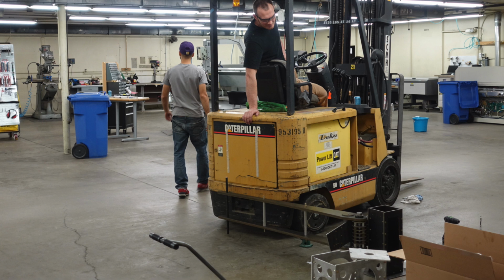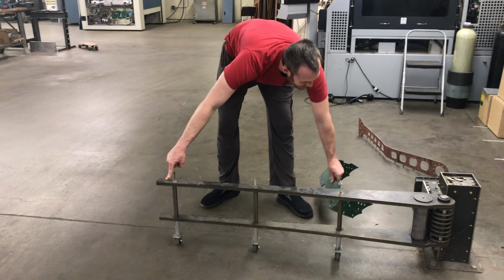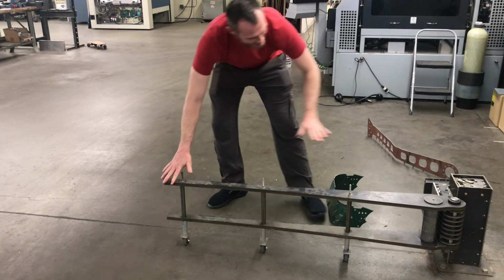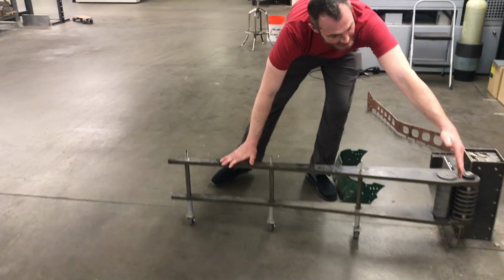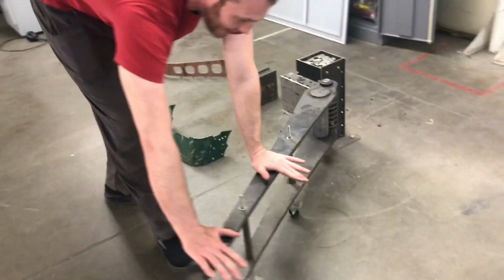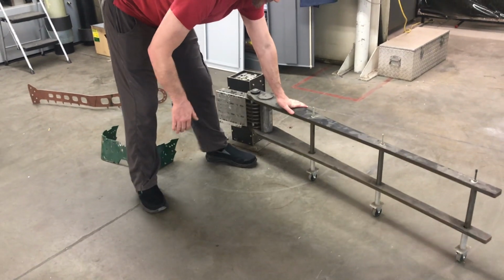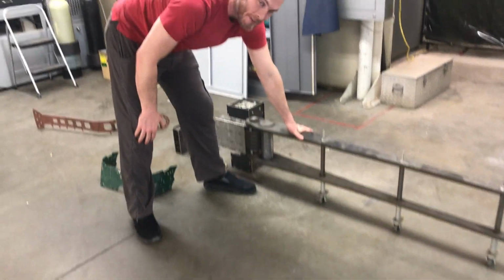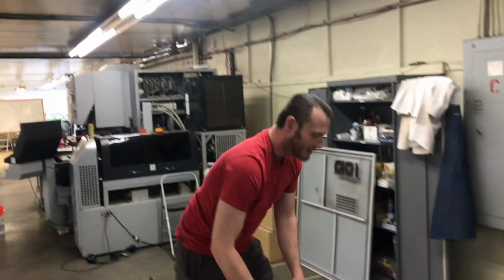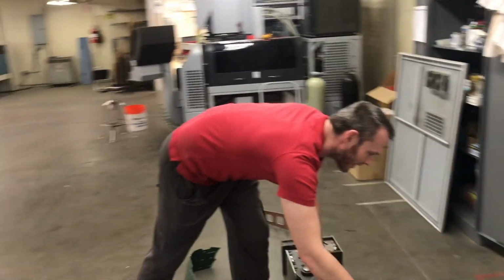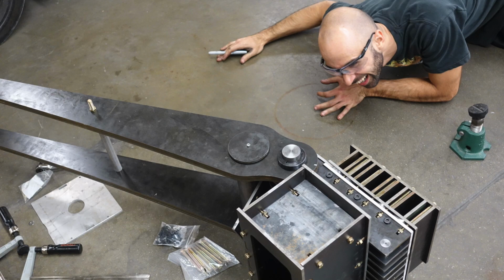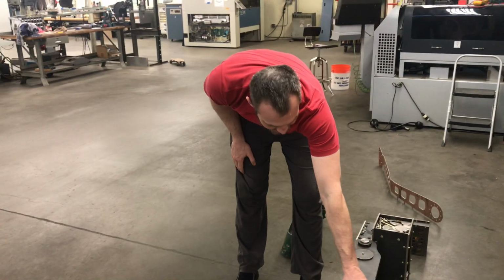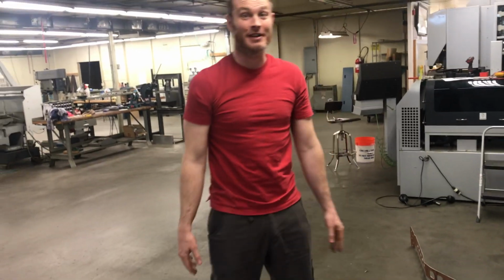We had to drive the forklift against this end of the arm. So we don't have any control at all. And so once you have your piece clamped here, sticking out into the room, you then drive this around, not to 90 degrees if you need a 90-degree bend, but because this material is so strong, you bend it to about 140 degrees, maybe 50 degrees of overbend, and it springs back from that to 90 degrees. That took a lot of experimentation to get right.